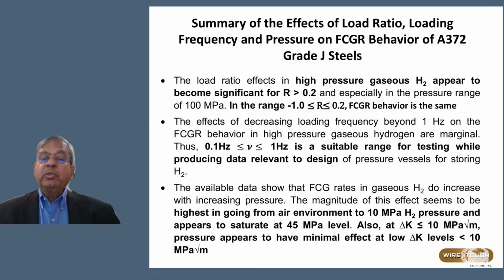The available data show that the fatigue crack growth rates in gaseous hydrogen do increase with increasing pressure. The magnitude of this effect seems to be highest in going from air environment to 10 MPa hydrogen pressure and appears to saturate at the 45 MPa level. Thus, at delta K less than or equal to 10 MPa root meters, pressure appears to have minimal effect.